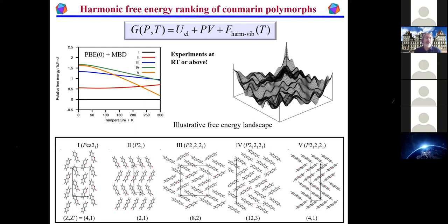So you can predict crystal structures, but real crystals are always at finite temperature, and the real figure of merit in terms of predicting and ranking them should be free energy. Right? Now, what people often do, of course, in this field is they use the harmonic approximation, and so they use a formula like what I've given above here, that the free energy is going to be the electronic potential energy plus a PV term and then some harmonic vibrational term. And you can make this quasi-harmonic if you want, try to minimize the volume or the unit cell parameters once you have the frequencies. Well, the problem is, if I do this, let's say, for the coumarin polymorphs, all right,